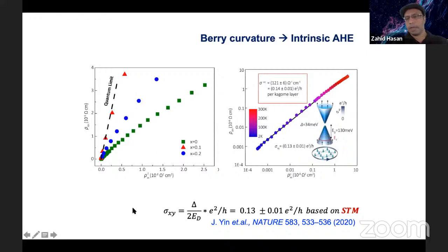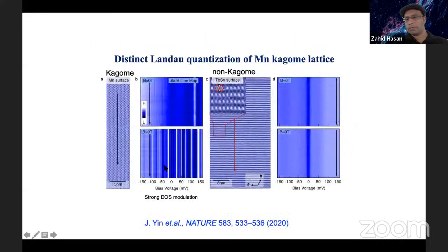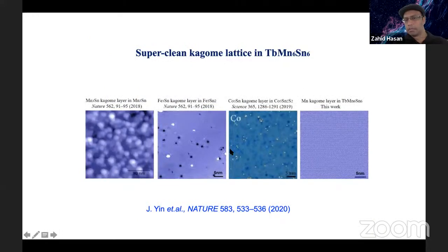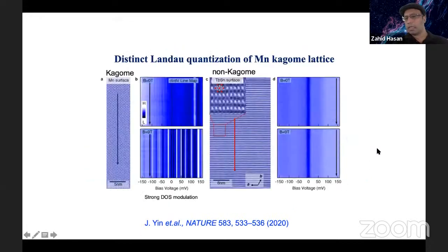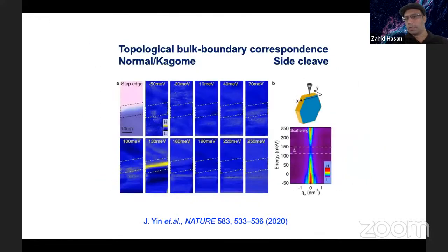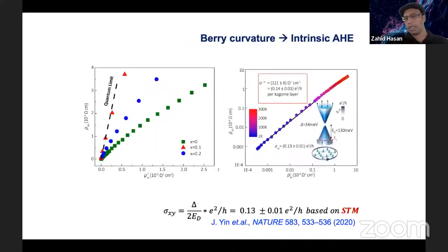The gain is that you are then at the quantum operation limit, your Fermi level inside the gap, so that when you do transport in a device setting, you should only see the edge state, not the Dirac state, just the edge state. But the price you pay is that you're messing things up by introducing dopants. But these compounds have a much smaller gap and are much more non-ideal. So the fact that we have a situation like that is already an important advance. And the most important advance is that the gap is large, even though you have to dope.